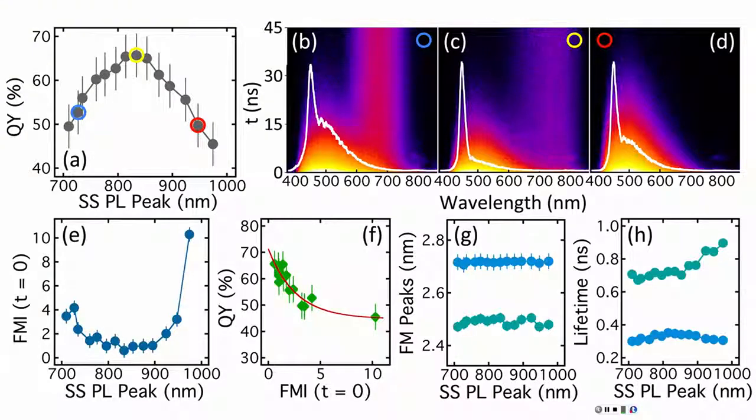You expect that you might create defects at different positions, and then this defect technically can have a shift in energy, right? Why is it so constant and not dependent at all? That's a good question. Why is it way up here and not in the middle of the gap like it usually is? If it's a surface defect, that usually means dark, right? Yeah, why is it blue shifted, not red shifted? That usually means you got some kind of bad state out here and you end up here and then it goes dark. But this is clearly much, much bigger in energy.